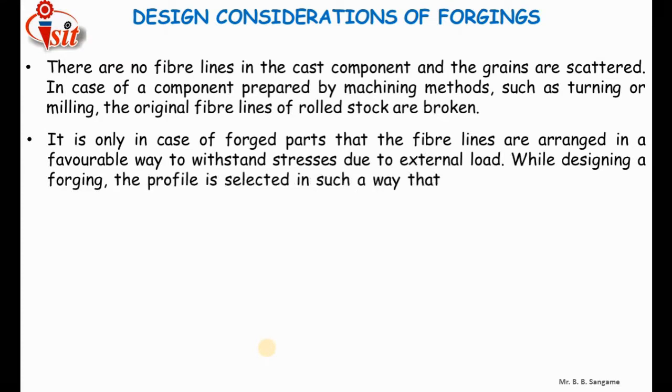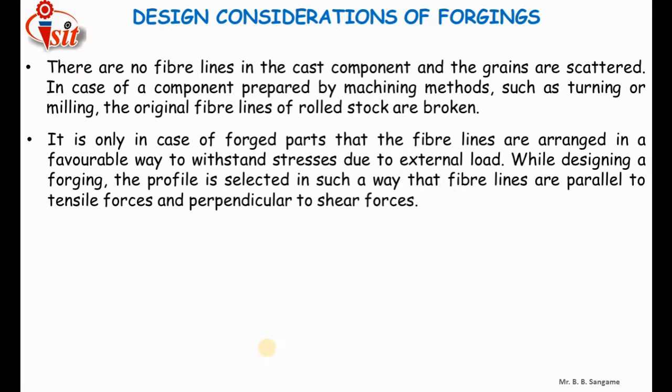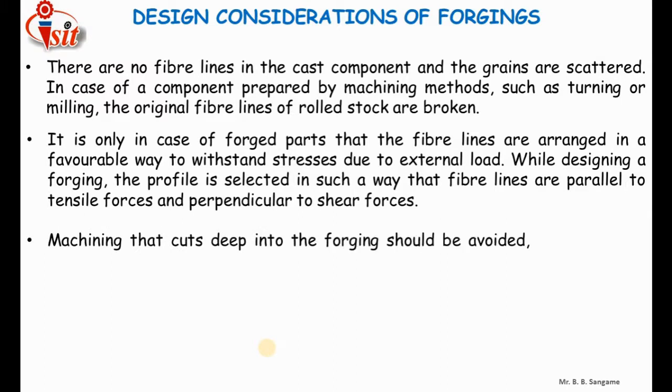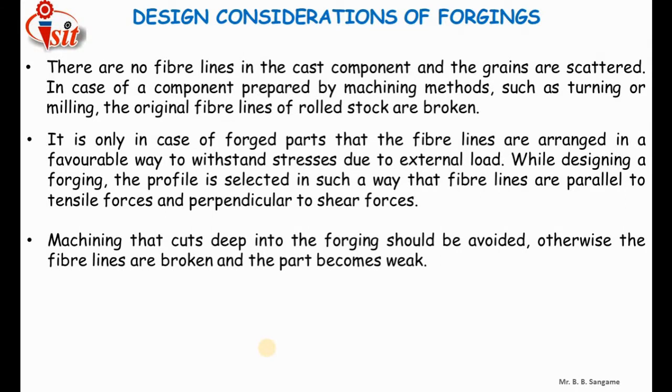While designing a forging, the profile is selected in such a way that fiber lines are parallel to tensile forces and perpendicular to shear forces. So this care should be taken while designing a forging. Machining that cuts deep into the forging should be avoided. Otherwise, the fiber lines are broken and the part becomes weak.